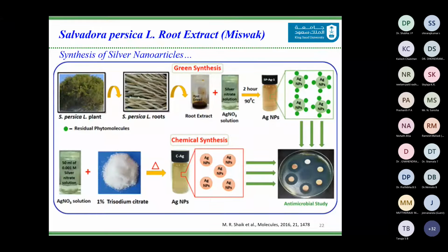And these roots were collected, and the extract was removed. And as you can see in this pictorial representation, the root extract was mixed with silver salt, and we obtained silver nanoparticles in 2 hours. These silver nanoparticles were subjected to antimicrobial analysis. However, in this study, we compared the green synthesized silver nanoparticles with the chemically synthesized silver nanoparticles.